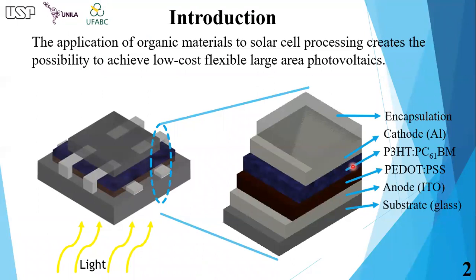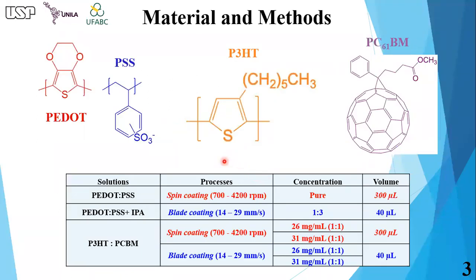The thin films were deposited by two different techniques, spin and blade coating. The layered structure of the manufactured organic solar cells is shown in this image. The PEDOT:PSS solution was deposited via spin coating as received. IPA was added at a volume ratio of 1 to 3 in blade coating deposition. The volume of solution used per sample of 1 square inch was 300 microliters for spin and 40 microliters for blade.